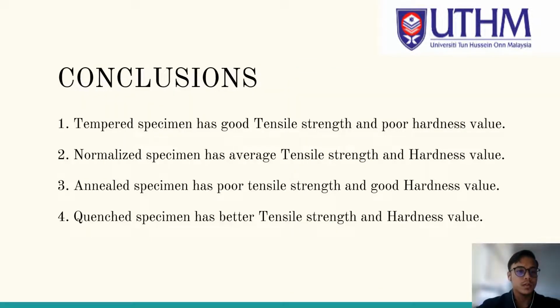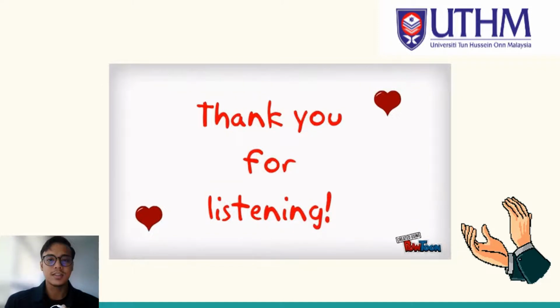Alright, I will continue for the conclusions. Number 1, tempered specimen has good tensile strength and poor hardness value. Number 2, normalized specimen has average tensile strength and hardness value. Number 3, annealed specimen has poor tensile strength and good hardness value. Number 4, quenched specimen has better tensile strength and hardness value. Thus, the heat treatment process was carried out on aluminium 6063 alloy and its mechanical properties were investigated. Thank you for listening to our presentation.